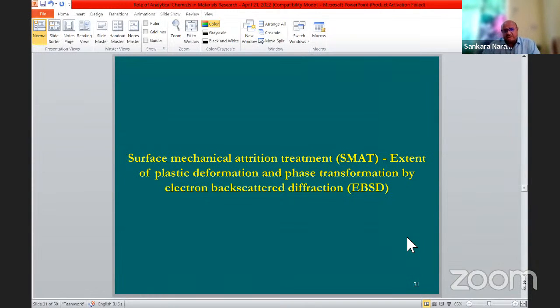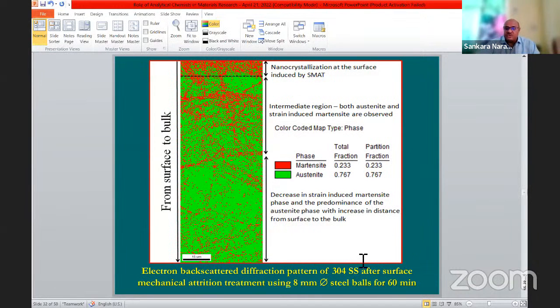For the same surface mechanical treatment, you can analyze the extent of plastic deformation and how much phase transformation is taking place by using electron backscatter diffraction pattern. So this is a very good analytical technique, attached with the scanning electron microscope. So what we did is basically we analyzed the structure. This is from the surface to the bulk, and the top layer, you could see the grain sizes are very much refined.